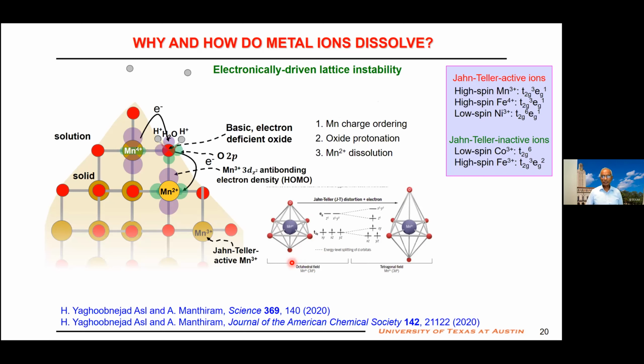Whenever you have one electron in the eg band, the e orbital, because these ions are in the octahedral site, they will have either static Jahn-Teller distortion or dynamic Jahn-Teller distortion. Nickel has dynamic Jahn-Teller distortion. It has one electron in the eg band. Manganese 3+ has one electron in the eg band. It has static Jahn-Teller distortion. Whenever we have that, they will tend to charge order, followed by protonation, followed by disproportionation, and that leads to metal dissolution. Cobalt, all electrons in the t2g band. Cobalt is the most stable and doesn't dissolve. Manganese is the worst, dissolves more. Nickel is in between. Cobalt is the best in terms of not dissolving.